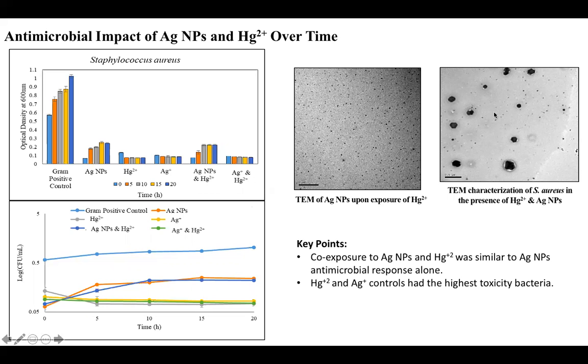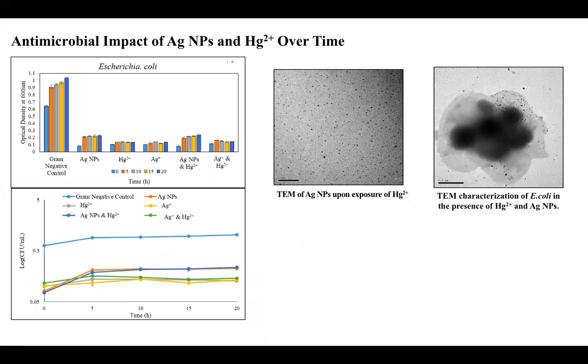And if we look at the Staph aureus, again, there's a breakdown in that growth of those bacteria. So you can see it a little bit more in how they're not as big as our other one, but we do still see them concentrated with nanoparticles around in that dissolution a little bit. So it shows us that there is some type of difference occurring with the co-exposure than independently.